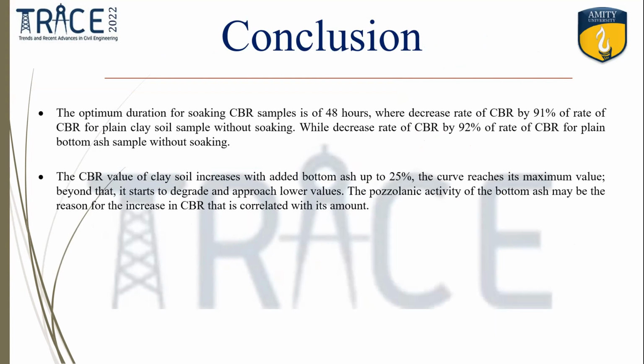Conclusion: the optimum soaking duration for the CBR sample is 48 hours, with the CBR decreased by 91% of the CBR of the plain clay soil sample without soaking, while it decreased by 92% of the CBR of the plain bottom ash sample without soaking. The CBR value of clay soil increased with added bottom ash up to 25%. The curve reaches its maximum value at this point, then it starts to decrease at higher values. The pozzolanic activity of the bottom ash may be the reason for the increase in CBR. This is correlated with its amount. Thank you.